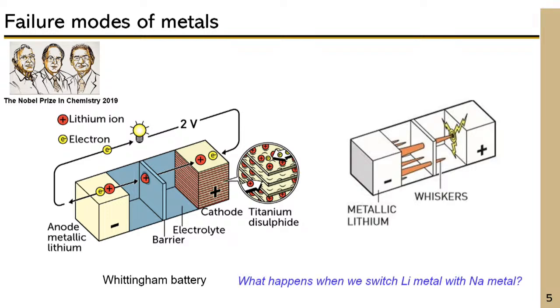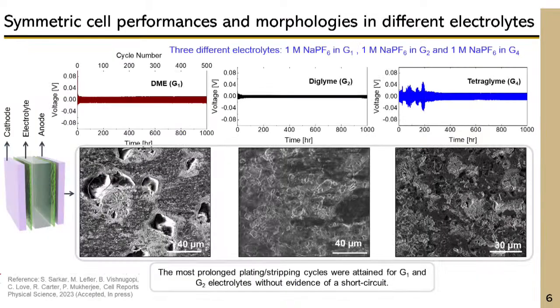So now, since I'm interested in the next generation of batteries involving sodium, I wanted to see if we replace lithium with sodium, whether we would see similar observations and if we are able to stop this kind of phenomenon. For that, the electrolyte plays a very big role in determining whether you will get these whiskers or not. So I selected 3 different electrolytes: monoglyme, diglyme, and tetraglyme.